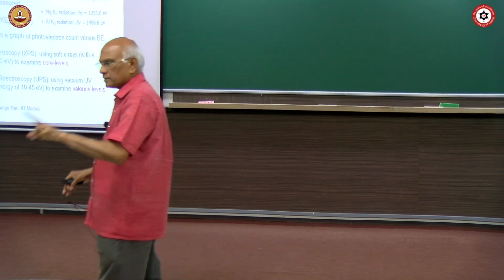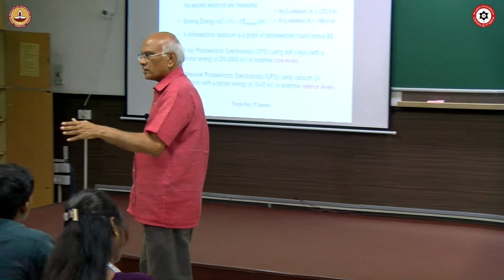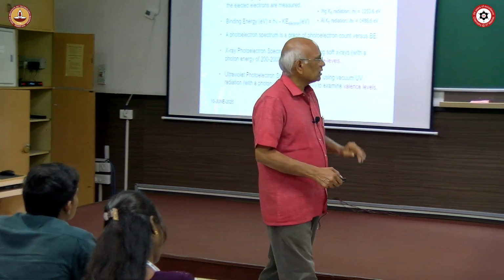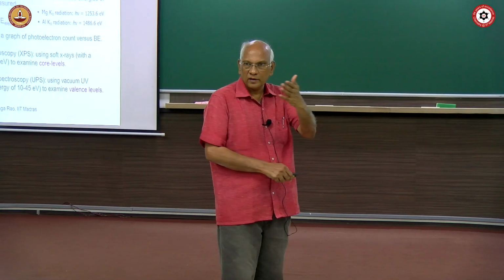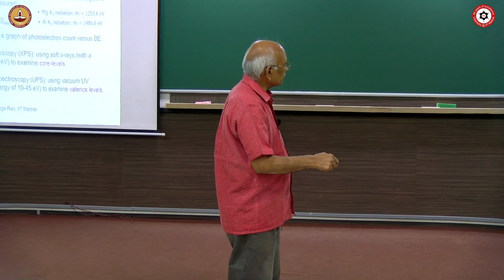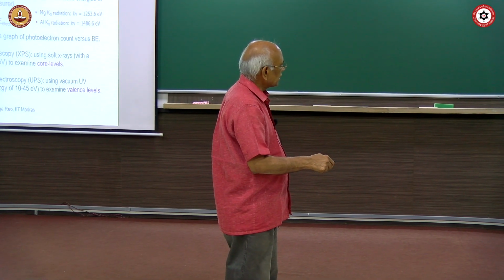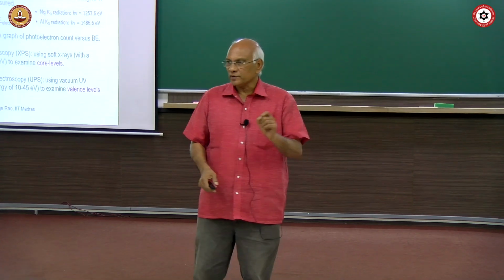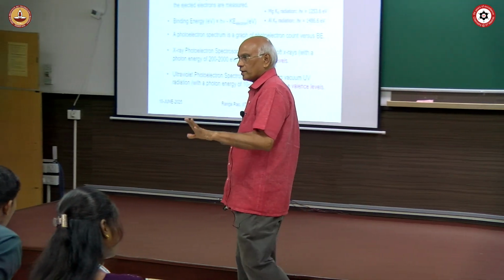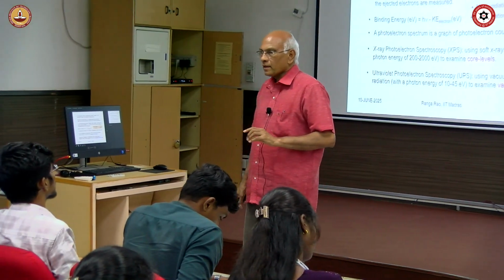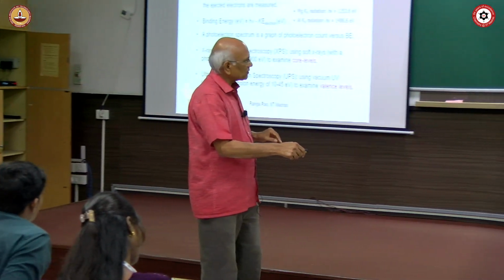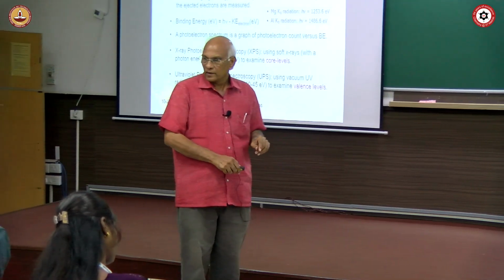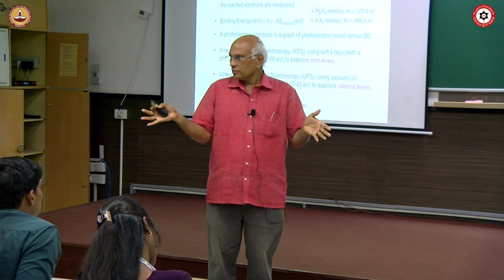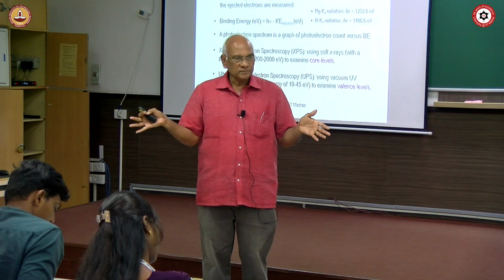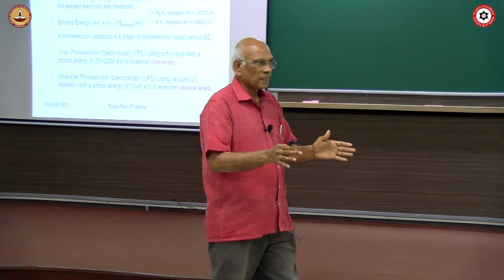The binding energy plus kinetic energy is equal to h nu, the photon energy that you are using. What photon energies do we generally use in laboratory equipment? Magnesium K alpha radiation, which has 1253.6 electron volt, and aluminum K alpha radiation, h nu equal to 1486.6 electron volt. These energies are very precise, they are monochromatic. Because only if we know the h nu value precisely will we be able to estimate the binding energy. If h nu keeps varying, then you will not be able to get the binding energy correctly, right. So, h nu has to be precisely defined.